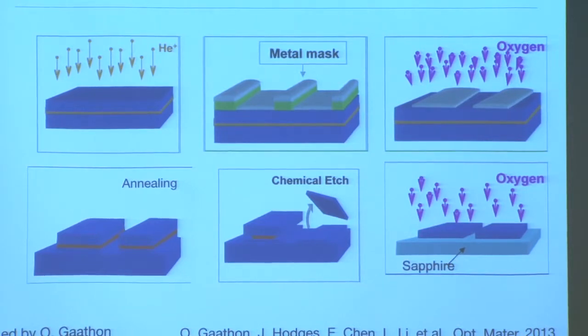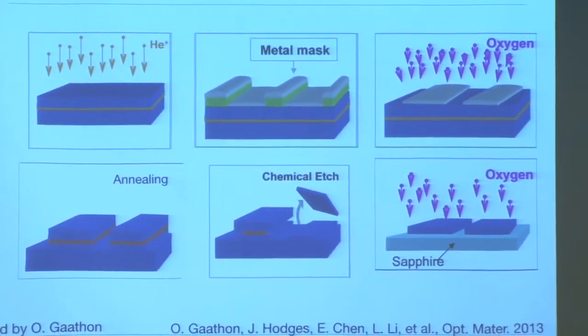How wide? It's about 100 micron by 100 micron. How thick? Eventually, they became 200 nanometers. What energy helium ions do we use? It's about 1.6 MeV.